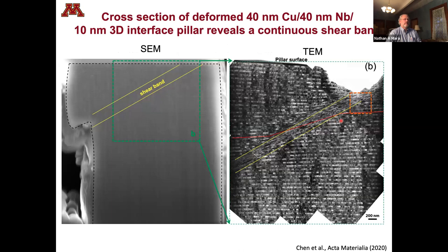If you put it in the TEM and you follow a layer all the way across the shear band, you notice that it remains continuous, just like we had in the 2D case. But here we have a very high interfacial shear strength. We actually just measured this. These are fresh results. So the mechanism that is operating behind this process has to be different. You zoom in on the region such as this.